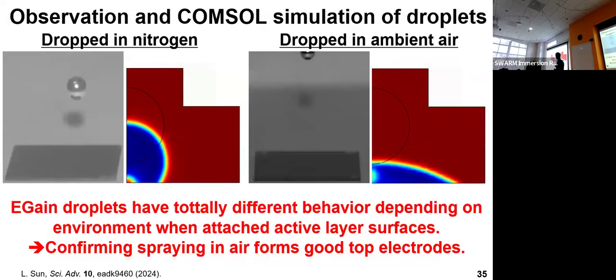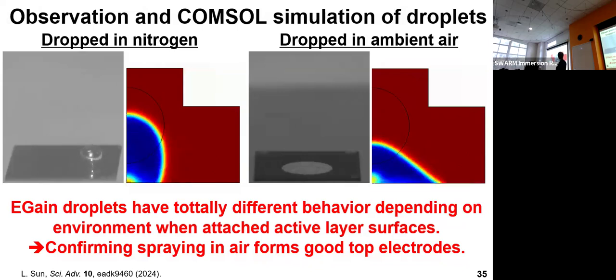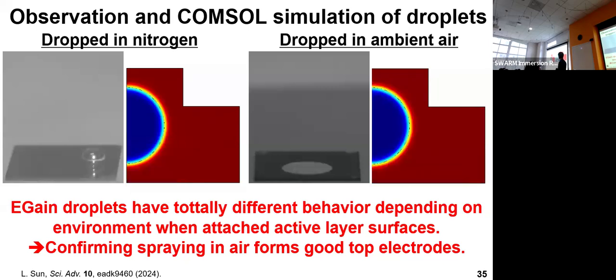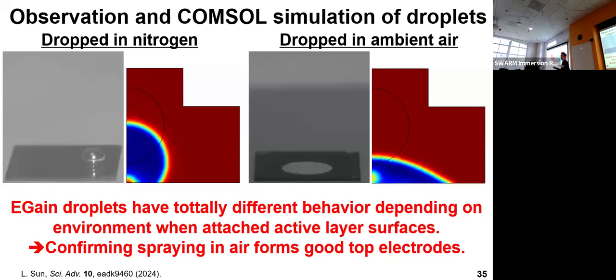And then we did the observation and we did the simulations to confirm the wettability differences in the different ambient conditions. When we dropped it in nitrogen conditions, there is no oxidation on the surface of the EGaIn, so the wettability was poor. But when we dropped the EGaIn in ambient air conditions, the surface of the EGaIn was oxidized quickly. Then such oxidized layers help to make a uniform wetted film, as shown here. This was also confirmed by the COMSOL simulation as shown here.